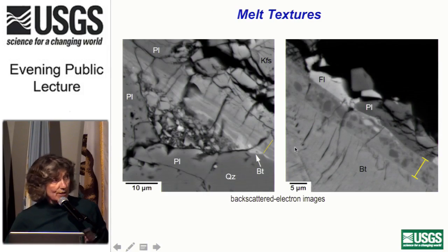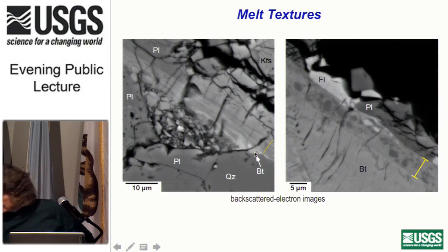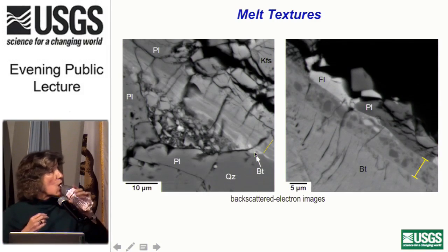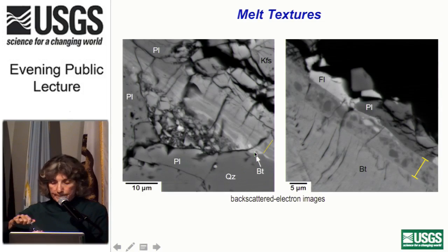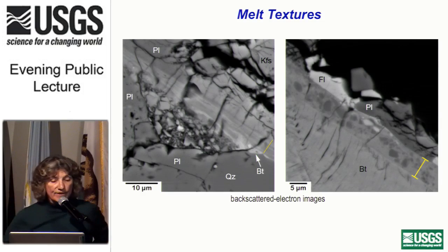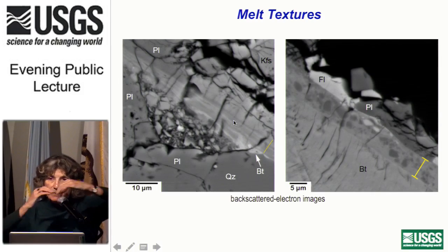So this slide here shows a couple of other interesting textures. In the photo on the left, this was the sawcut surface, and a little depression in the surface got filled with ground up mineral debris that basically got trapped in place as the melt went over. It's kind of sealing it off. And you can also see, again, this yellow band indicates the thickness of the layer. You can see a lot of compositional streaking here. It kind of indicates that we had laminar flow of the melt during the slip event.